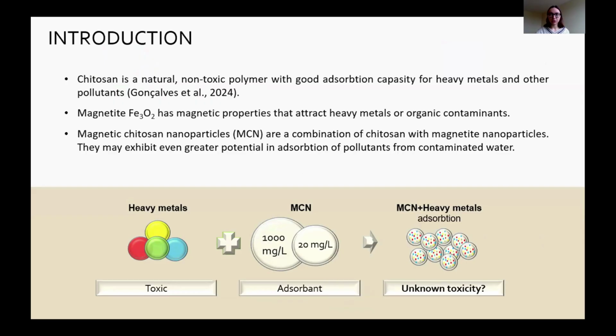And magnetite, on the other hand, has magnetic properties that attract heavy metals or organic contaminants. And it is also useful as it can be separated from other materials, washed and reused. So what we tested is magnetic chitosan nanoparticles, the MCN, that are a combination of chitosan with magnetite nanoparticles, and they may exhibit even greater potential in adsorption of pollutants from contaminated water.